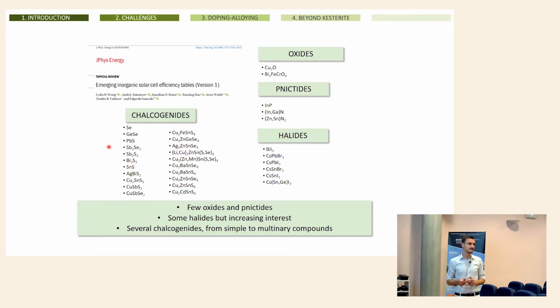In terms of stability, for the moment, we don't have any evidence that the material is not stable, it seems to be stable. What we found is that these interfaces can be unstable because the material, as I explained, is ribbons with van der Waals interspace. So once you put a contacting material, if you heat a bit, elements from your contacting material can easily diffuse through this van der Waals region. And normally we observe deterioration of the devices. If we use CdS, for example, the solar cells start to evolve quickly. So in some weeks, you start to observe that the device changes, and normally is deteriorated. And we have demonstrated also that it is because of the sulfur diffusion toward the antimony selenide.